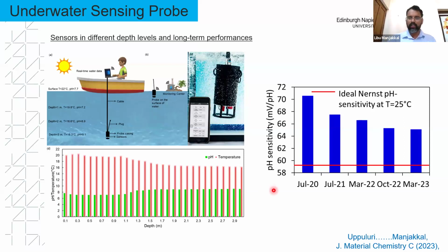We found that over, for example, almost 3 years, the sensing performance is almost stable. So if you want to map a river's pH value or the pH or temperature at different depth levels, the underwater sensing probe using screen printed based sensors will be a very good alternative to the current expensive sensing.